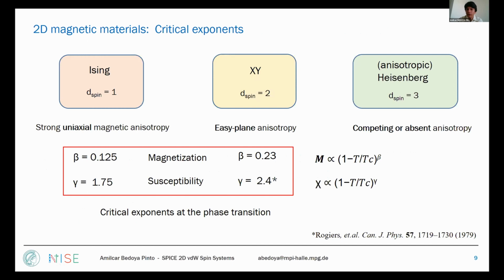There's a second manner in which you can distinguish these 3 different magnetic classes, not only by measuring the anisotropy, but also by looking at the details of the phase transition. At the phase transition, order parameters such as magnetization or susceptibility will decay with a power law, and this power law is related to critical exponents. These critical exponents, which I highlighted in the red box, are specific for Ising and XY systems. For Heisenberg, they have not been developed because the isotropic case usually has no magnetic order and thus no ferromagnetic to paramagnetic phase transition.